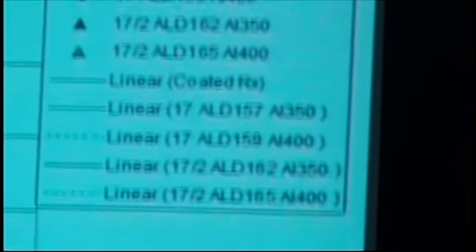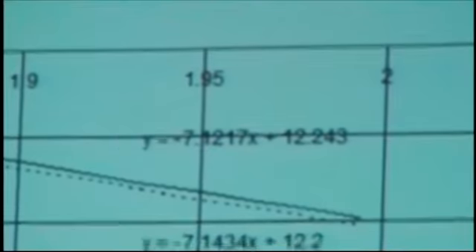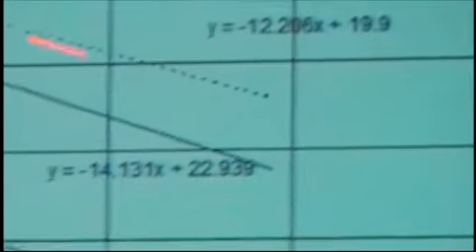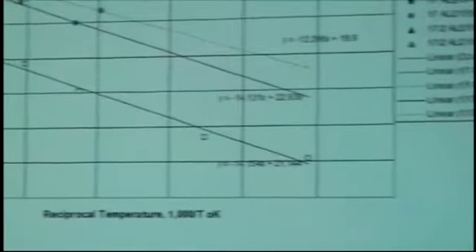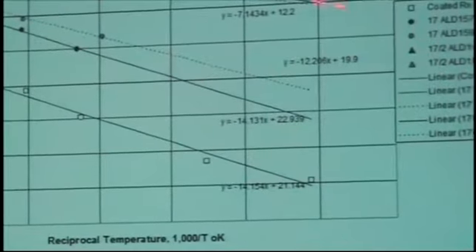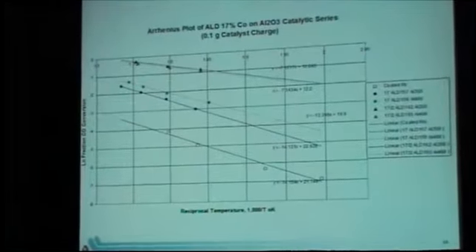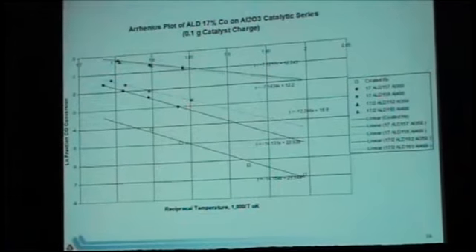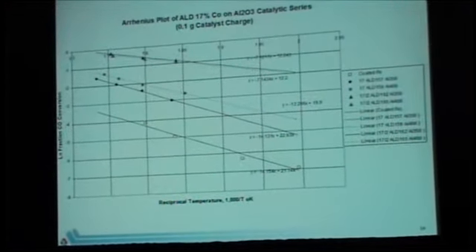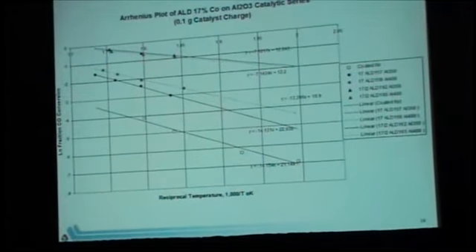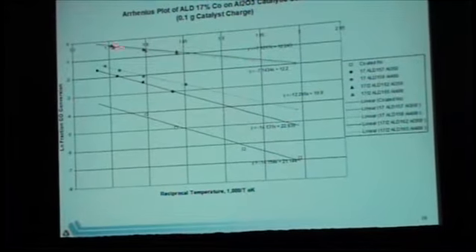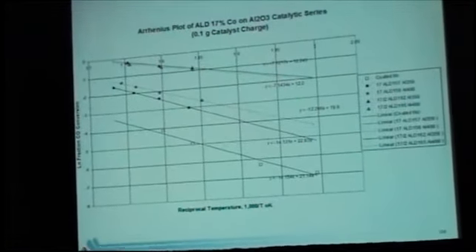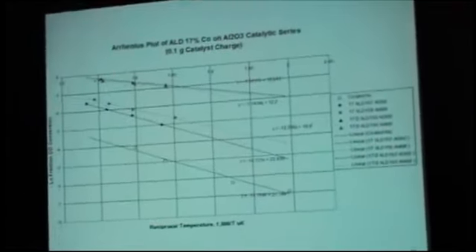In looking at the Arrhenius plots, again, the log of CO conversion versus reciprocal temperature, the activation energy in looking at the ALD deposited cobalt 400, 450, you're talking in this range. And when we went to the 2%, a very different activation energy. In here, the activation energy is in the order of about 30 kilocalories per gram mole, and up at the 2% platinum, it's about 14 or 15. Again, indicating a different mechanism.